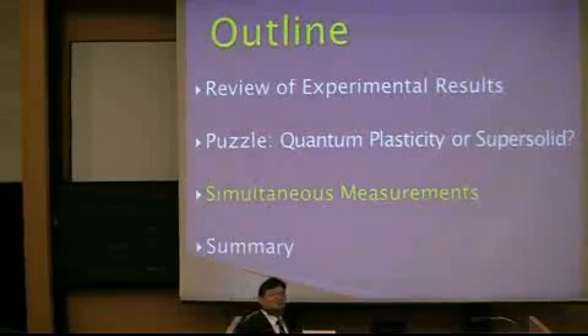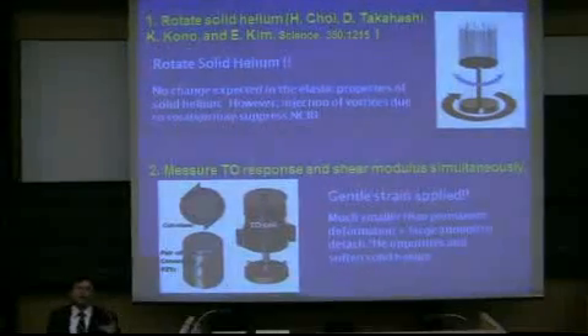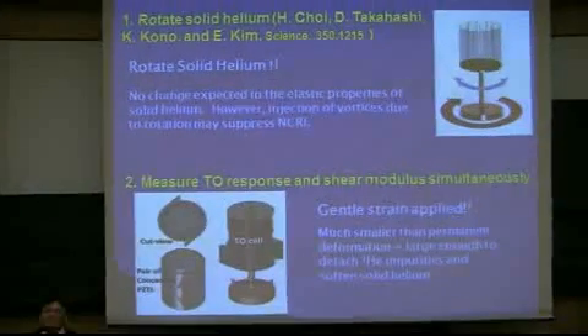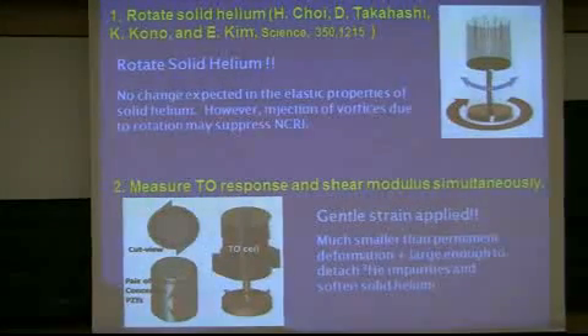Is this the end of supersolidity? Oh, wonderful. But from the beginning, I didn't believe that explanation. The reason is very simple. Even though this experiment possibly explained my second torsional oscillator experiment, the first torsional oscillator experiment was done with solid helium confined in a porous geometry. Elastic modulus change doesn't affect that measurement at all. However, people try to associate this shear modulus with the torsional oscillator experiment. That's why I had to do other experiments to find more solid and firm supporting evidence. That's why I did two experiments, not just one.